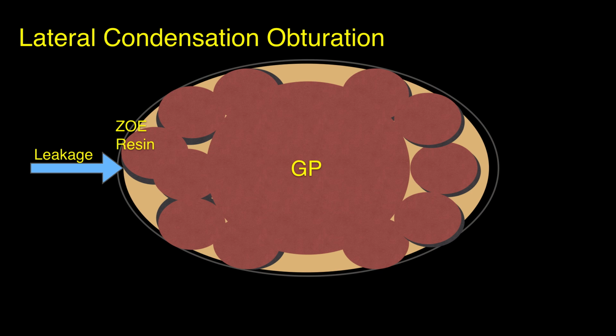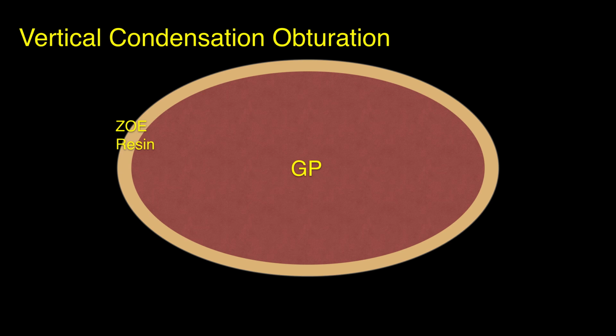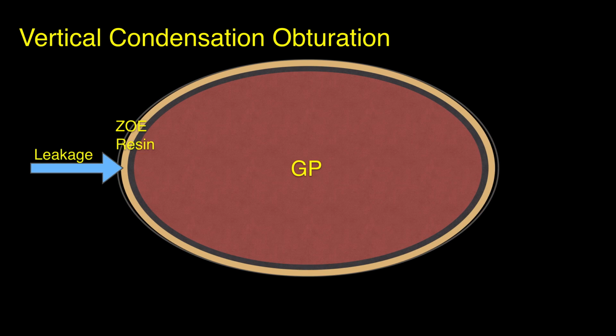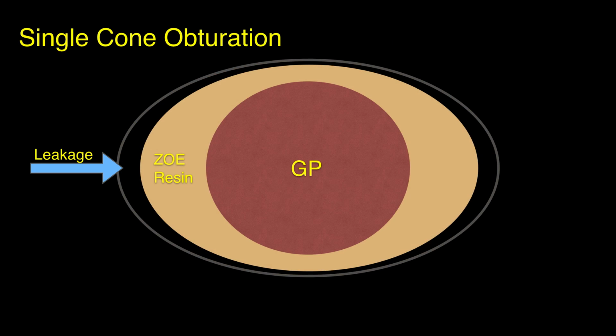So vertical condensation came about to address that issue by putting even more gutta percha in there and reducing the sealer interface even more. But then again, you still got the same issue of leakage even with vertical condensation because the gutta percha shrank again 2 to 7%, and also the sealer came off the walls as well. So the same issue. Of course, they were all better than the original single cone technique, but they were not quite as ideal as they could have been until this whole thing was resolved.